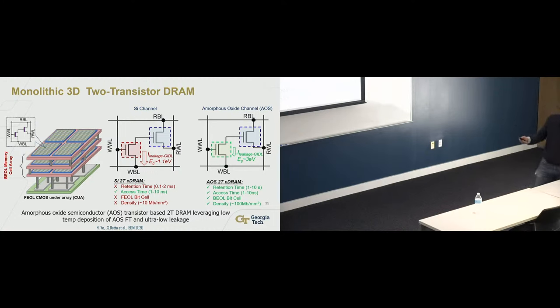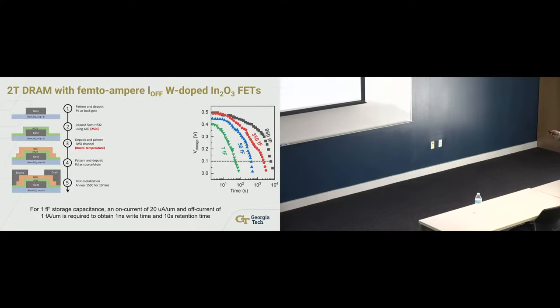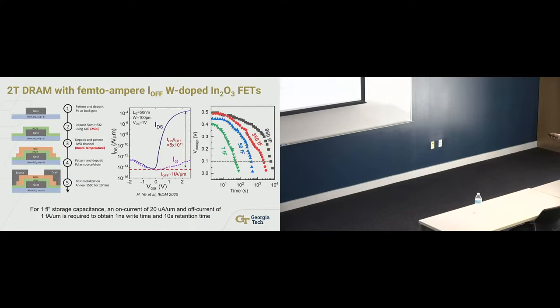But if you can do that, then you can actually get rid of the capacitor of the DRAM and just store the charge at the gate capacitance of a read transistor. But that's a very tiny charge. That charge will easily go out if this transistor is not completely cut off, okay? And you have to demonstrate this at 85 degrees C. So you need a transistor with extremely low leakage, almost like an open circuit. We have had some progress in this area, and we have since then improved this: 10 to the power 11 on-off ratio, 11 orders of magnitude.